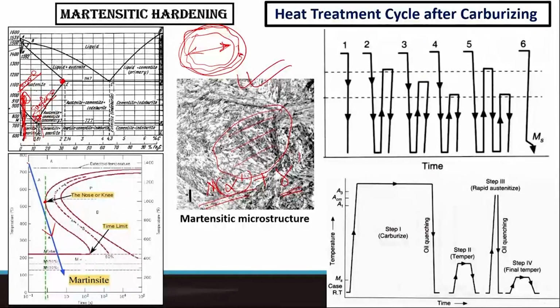So that is why all carburizing treatments, be it solid, liquid or gaseous state, have to necessarily go to a temperature above AC3, or in the austenitic loop, the pure single phase austenitic loop. So this is how we actually enrich, and during the enrichment process we have to heat, and this typically is your AC3 and this is AC1. So we have to necessarily heat to above AC3 in all these various thermal cycles which are possible.